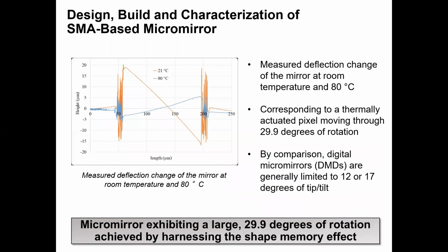So using the laser confocal microscope, a 3-dimensional image of the full shutter pixel was recorded at room temperature in the unactuated condition, and at 100 degrees on a hot plate in the actuated position. So this allowed for a line scan to be plotted to assess the deflection or angle of the micromirror in each of the actuated and unactuated positions.